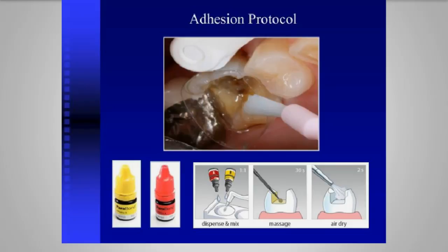And when I say that, there's no universal standard. The dentist should do this, not the assistant, because when you blow with a vortex of air, a high velocity, where does your adhesion go? Does it stay? So a very light air stream to just let the chemistry work, and do not light cure